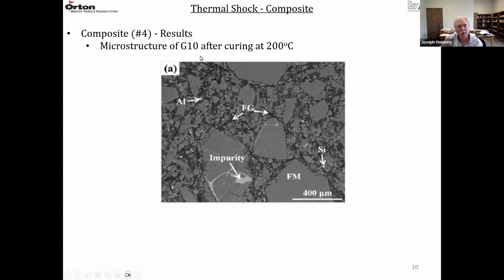So this is the microstructure of G10. That's without any MgO carbon pellets, cured at 200 degrees C. So FM is the fused magnesia grain. You can see that it's basically pore-free. It's very dense, fused cast.